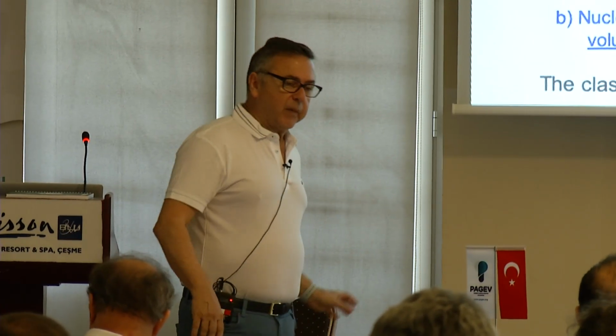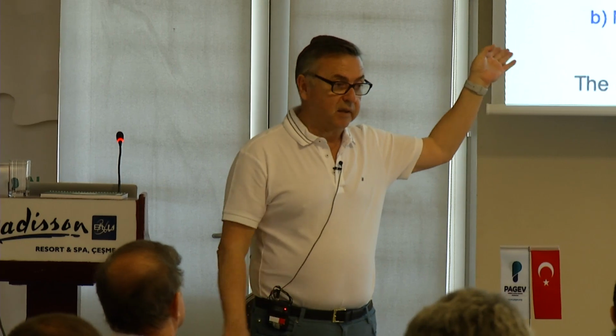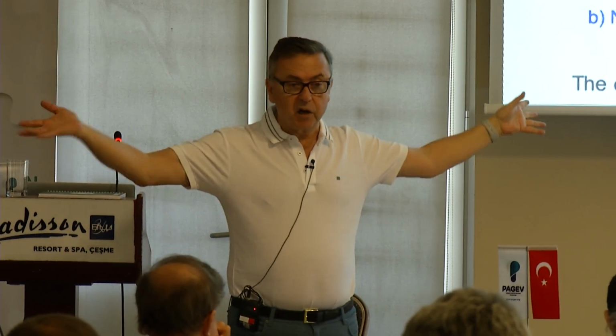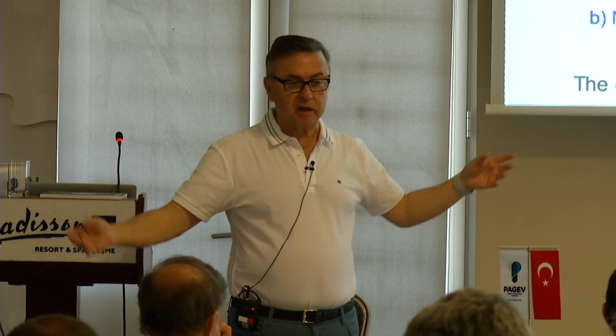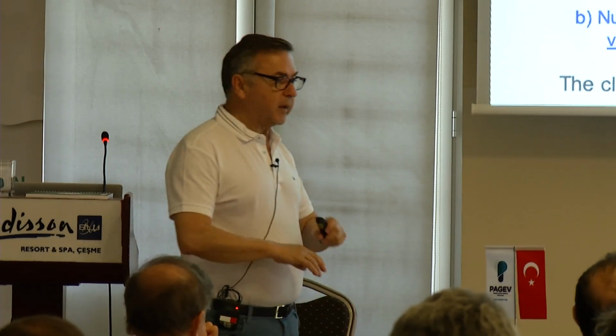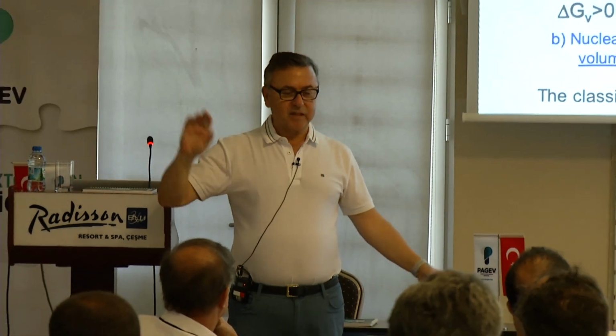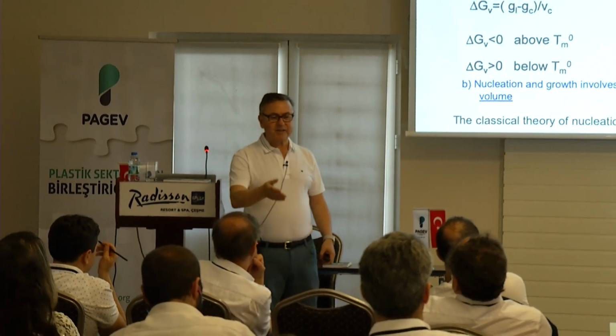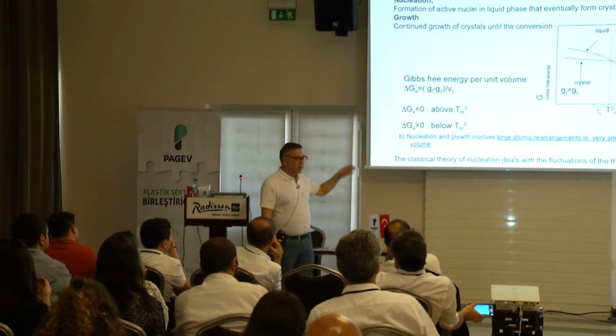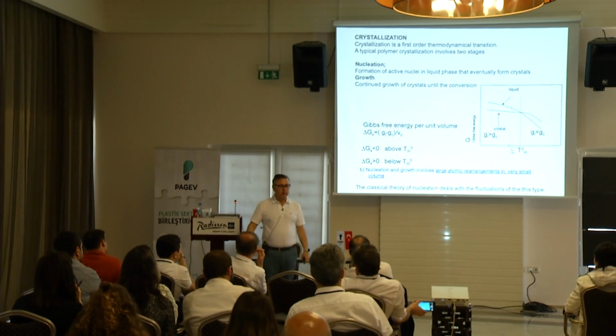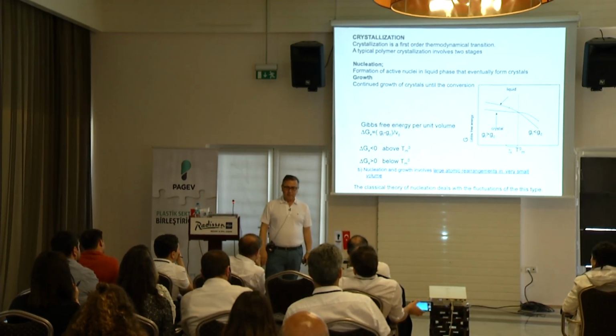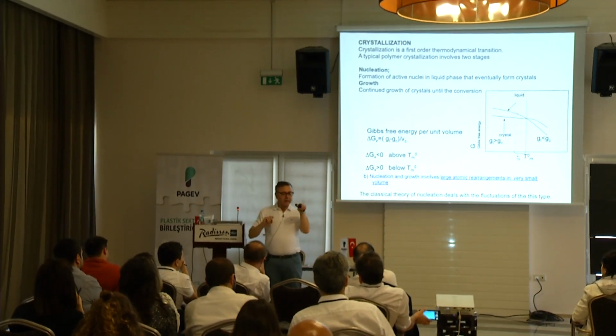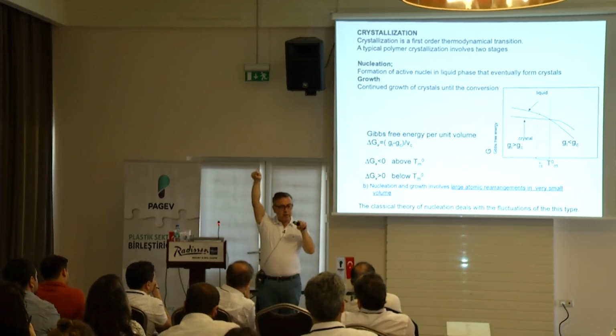So essentially, an ideal situation that you never get in a polymer. You don't measure this in DSC. This is a hypothetically extremely large crystal, almost infinitely large, that will give you that maximum temperature. What is the melting point of polypropylene? 167? Wrong. That's not an equilibrium melting temperature. Equilibrium melting temperature of polypropylene is around 200 and something. What that tells you is you are at 167, but the real thing is 220.